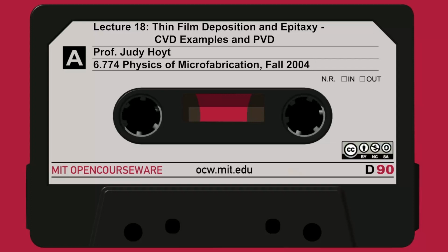And in this deposition rate term here on the left is this equation for the velocity, the deposition rate. N is the density of the material being deposited. So here's a very simple formula to calculate the deposition rate of your reactor. It's the evaporation rate, which you'll have to calculate. It depends on the temperature and all that. Divided by the solid angle times the density times R squared. And there's a cosine theta, theta sub k here. So theta k here is this angle right here. So as I take a wafer and move it from right here along this line, the deposition rate is going to go down according to this cosine function.